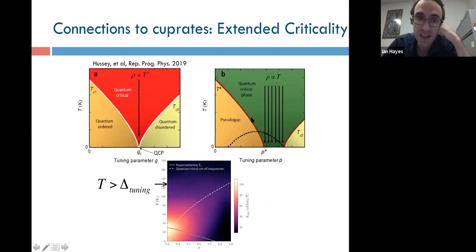And this is nicely laid out in a paper by Nigel that contrasts the way criticality seems to emerge in pnictides and cuprates, whereas in the cuprates, you seem to have an extended region of some sort of critical behavior going up to the edge of the superconducting dome. The pnictides up until now have seemed more conventional critical systems in the sense that things are concentrated really near a point where the antiferromagnetic order ends. I think one takeaway of this observation is that there is more of a connection between these two scenarios than may have originally seemed to be.